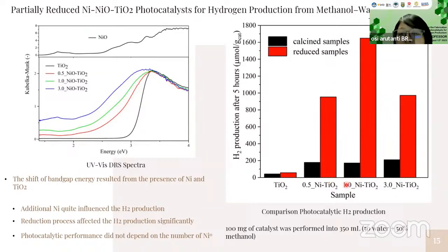But here the optimum condition was a ratio of 1, because the excess of Ni resulted in a decrease of hydrogen production. Here we assume that the excess of oxygen vacancy can reduce hydrogen production due to the presence of electron-hole recombination.